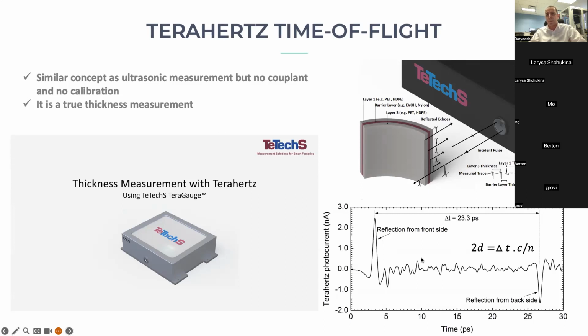What is happening in this measurement, the key element here is that the time between those echoes as they arrive gets measured very precisely with a sub-picosecond accuracy, which enables one to measure the thickness, in this case, with a micron level precision. And once you get that measurement, the math behind calculating the thickness is very simple. It is a true thickness measurement. It actually measures the distance, in this case two times the thickness, because the light goes a round trip, is equal to the time that it took for the light to travel times the speed, which is the speed of light divided by the refractive index of the material, which is a known parameter. So it makes it very simple math once you have the measurement done precisely and accurately.